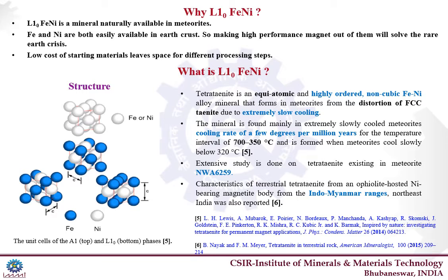L10 is a highly ordered structure where atoms of the constituent elements of the alloy occupy alternate planes. As in the case of the FeNi shown here, we can see that in FCC FeNi, the positions of Fe and Ni cannot be determined. But in the case of L10 ordered, as shown in the three structures below, the alternate planes are occupied by Fe and Ni.